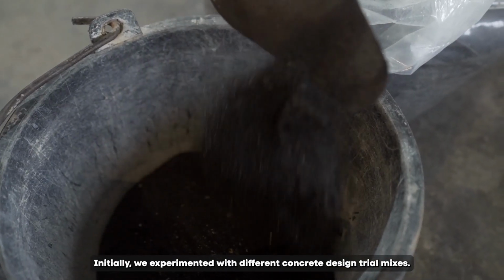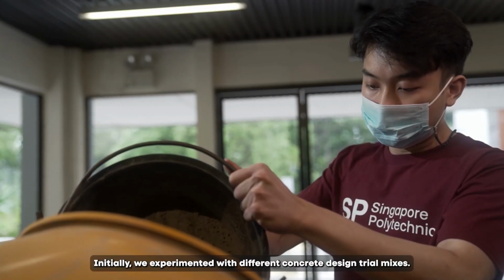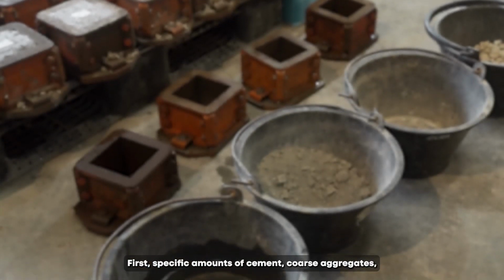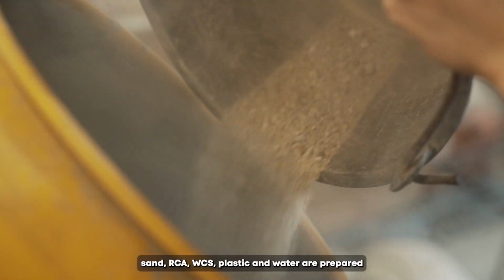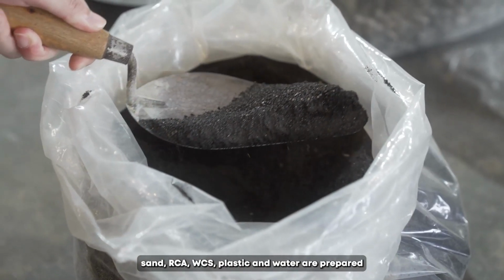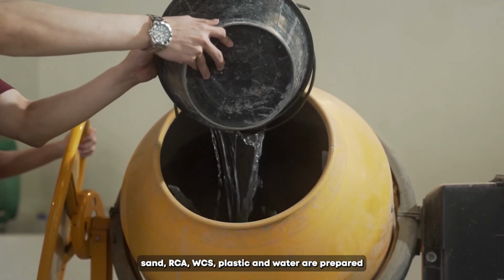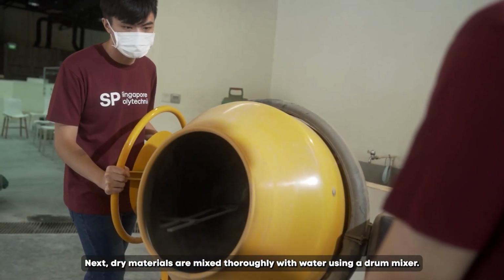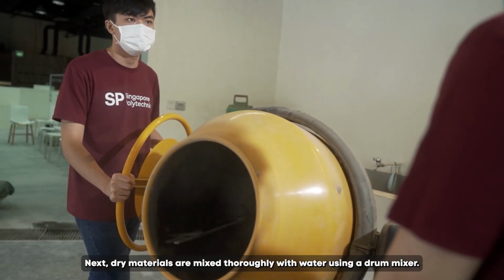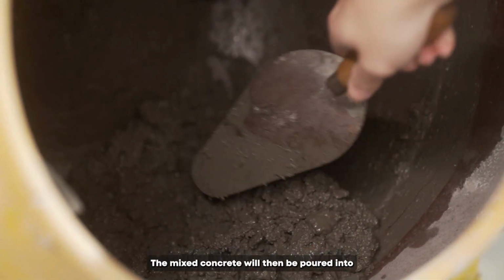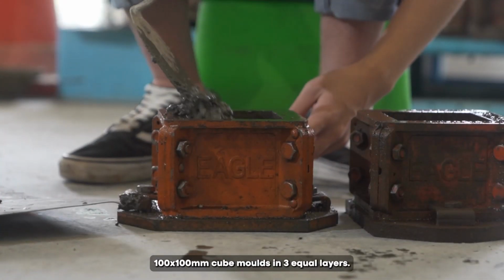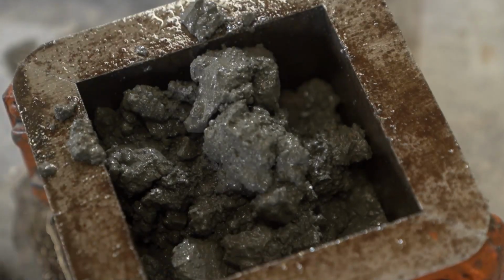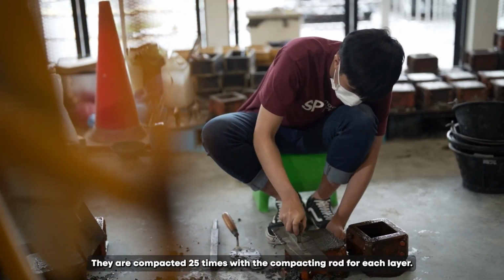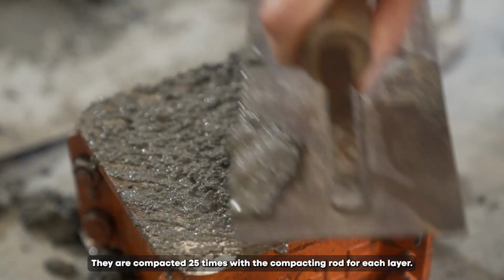Initially, we experimented with different concrete design trial mixes. First, specific amounts of cement, coarse aggregates, sand, RCA, WCS, plastic and water are prepared. Next, dry materials are mixed thoroughly with water using a drum mixer. The mixed concrete will then be poured into 100 by 100 mm cube molds in 3 equal layers. They are compacted 25 times with the compacting rod for each layer.